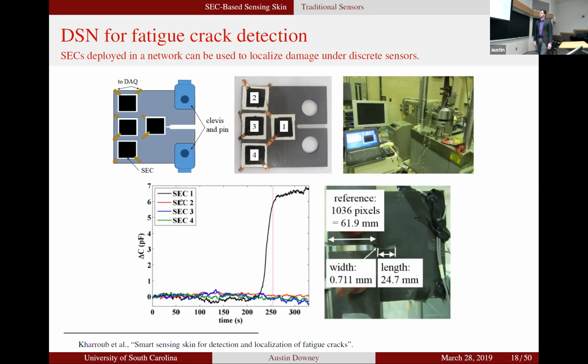And you can see that as the crack grows under SEC number 1, we get a large increase in our measured capacitance for SEC number 1. Pretty simple to understand, right? We have an opening of a crack, we have a change in deformation, and that's going to show up as a change in capacitance.